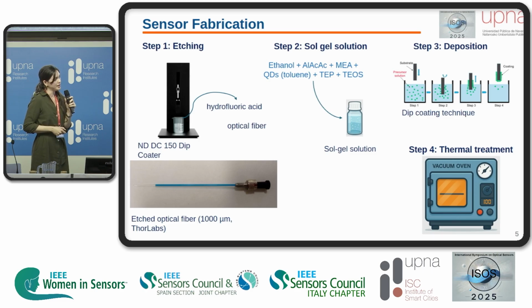And finally, thermal treatment at 100 degrees Celsius for 2 hours in a vacuum oven without oxygen, and after many nitrogen purging cycles. This optimized process allows us to stabilize the film, avoid oxidation, and minimize the effect of photobleaching, which is one of the main problems for luminescent sensors.